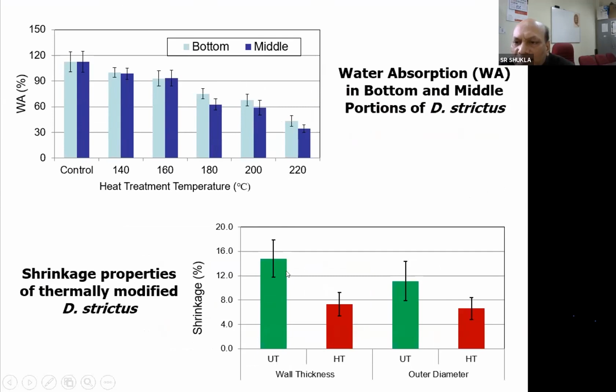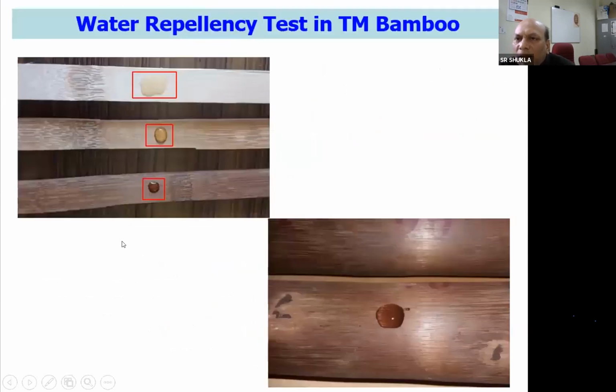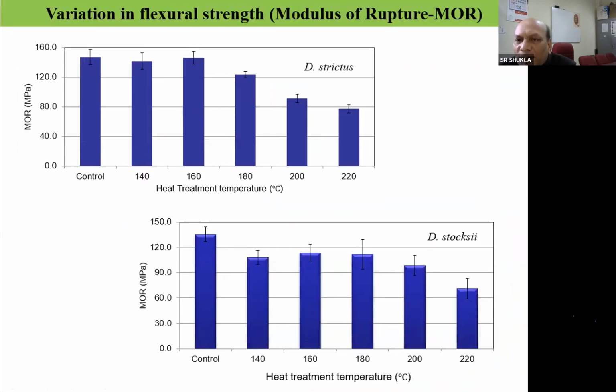This is the shrinkage properties. This is control one, untreated, and this is the thermally treated. So the amount of shrinkage and swelling will be less when bamboo is treated at higher temperature. Now this shows the untreated bamboo strip. You can see here a drop of water on the surface of the untreated, and this is the treated bamboo at lower temperature, and this is at higher temperature. So this drop remains like a drop only. It will not get absorbed, unlike the untreated control samples. So this shows that bamboo becomes water repellent after the treatment.